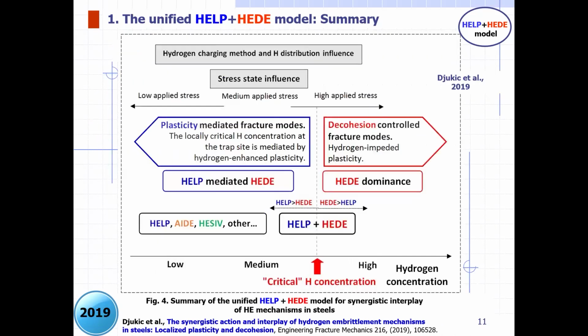So here is the overview about critical hydrogen concentration, HEDE dominance, HELP-mediated HEDE, and other plasticity-mediated mechanisms. As you can see, depending on the global hydrogen concentration, we can divide the behavior of the material into two categories. We have so-called plasticity-mediated fracture modes due to effects of hydrogen, and on the other side, we have pure embrittlement of the material, which means a decohesion-controlled fracture mode. Very interesting and very enigmatic to understand, hydrogen promotes the plasticity of steel and other materials at low hydrogen concentration, so it increases the plasticity of the metal.